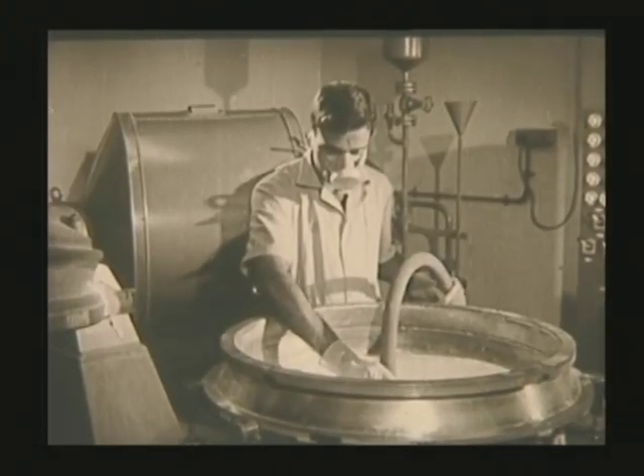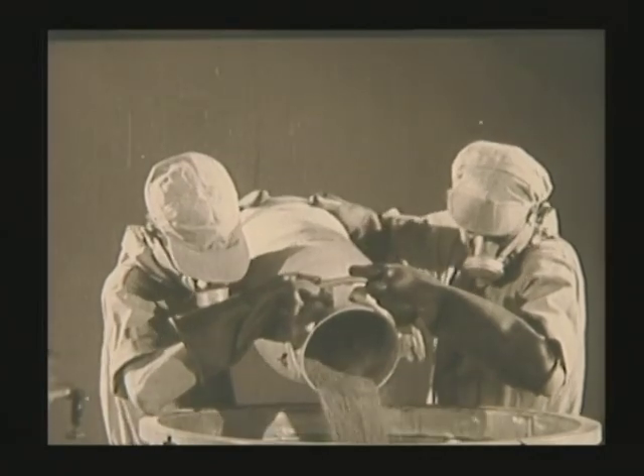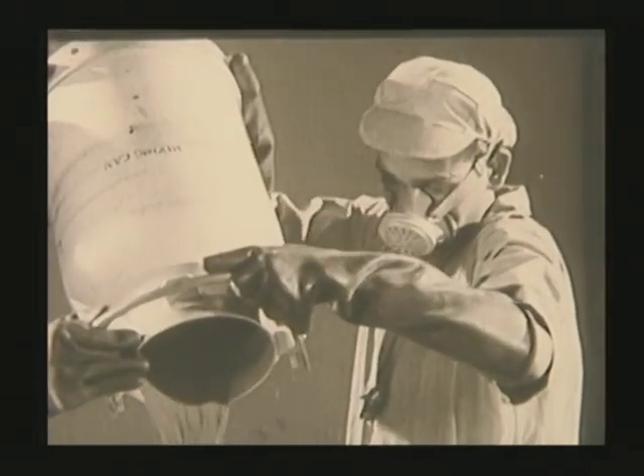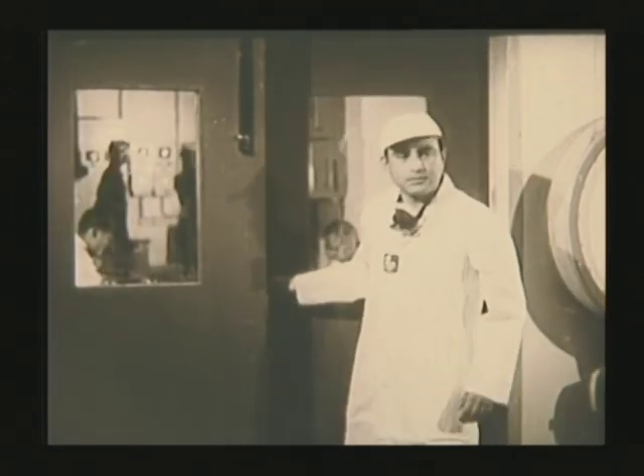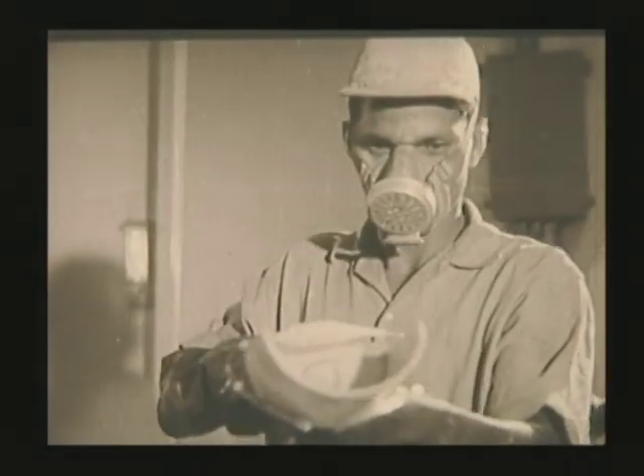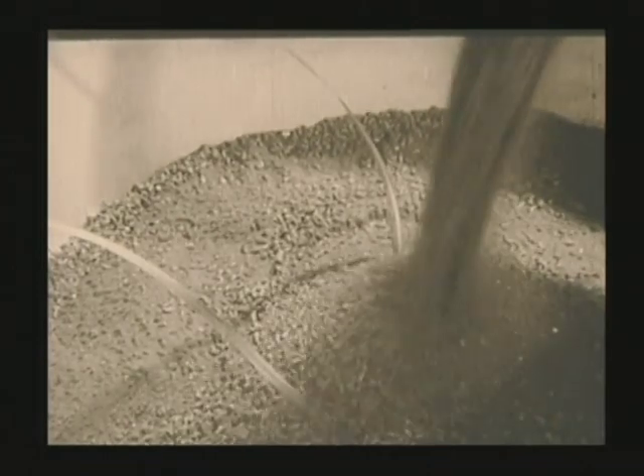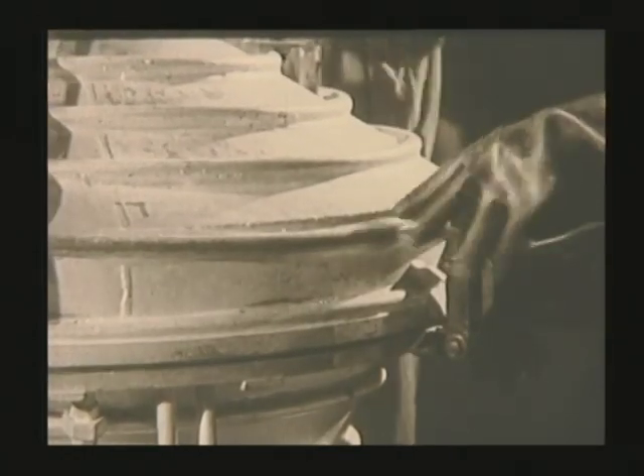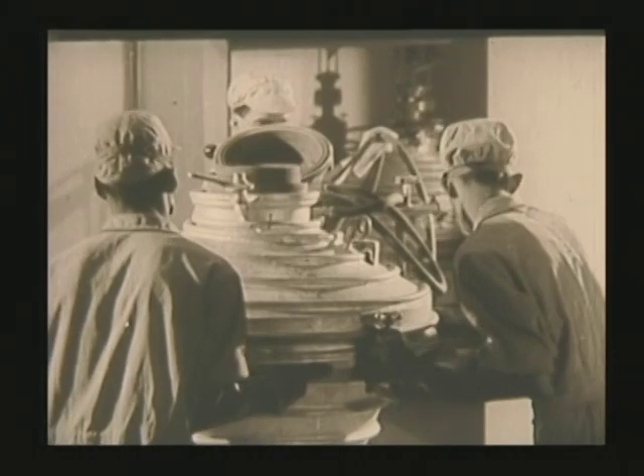The reduction vessel where the fluoride is reduced to metal is lined with dry calcium fluoride to prevent the hot molten metal coming in direct contact with the vessel. Uranium tetrafluoride is mixed with calcium metal granules and the mixture is poured into the vessel. A magnesium ribbon is very carefully attached to the contactors provided to ignite the mixture. The lid is then fixed and the vessel is moved to an isolated room.